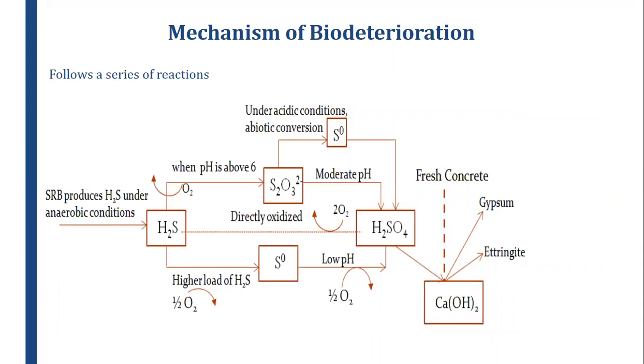The mechanism of bacterial biodeterioration of cement follows a series of reactions. In a sewage setup, for example, the sulfur-reducing bacteria produce hydrogen sulfide under anaerobic conditions, and the produced hydrogen sulfide undergoes oxidation by the sulfur-oxidizing bacteria to form biogenic sulfuric acid. The formed biogenic sulfuric acid reacts with the soluble cement portions to form gypsum and ettringite, as illustrated in this flow diagram.